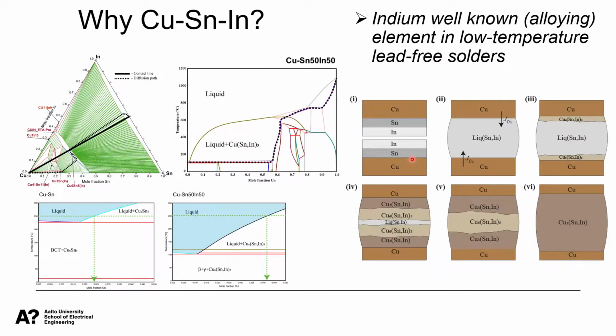Why we decided to study the copper-tin indium ternary system? It is well known from development of low temperature lead-free solders that indium has stabilizing effect on the liquid phase. Based on the available thermodynamic description from the ternary system, it is possible to evaluate the effects of indium additions to copper-tin system on the interconnection microstructures as well as processing capabilities. Based on the thermodynamic simulations, we can conclude that we don't expect significant differences in the interconnection microstructures in comparison to the more commonly utilized binary copper-tin system.